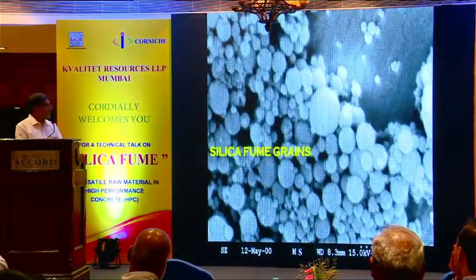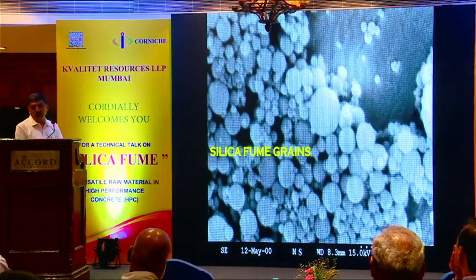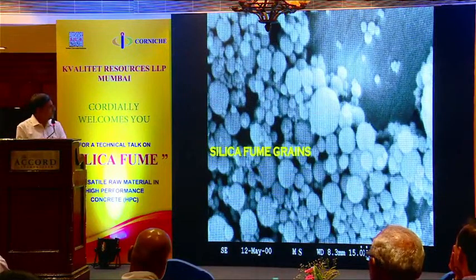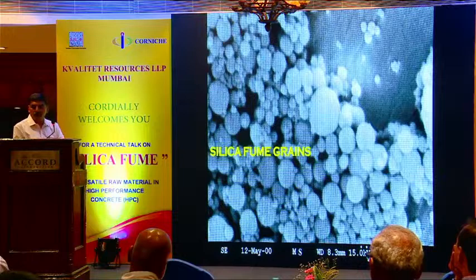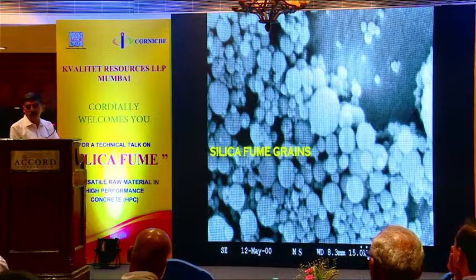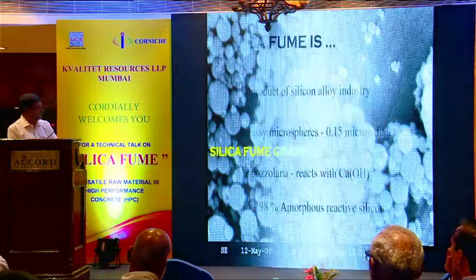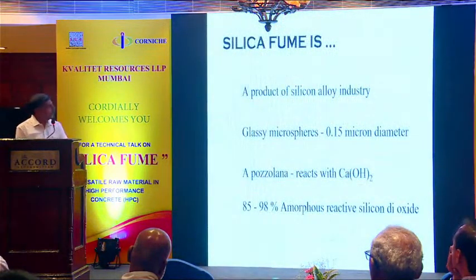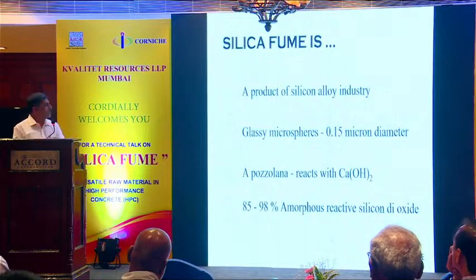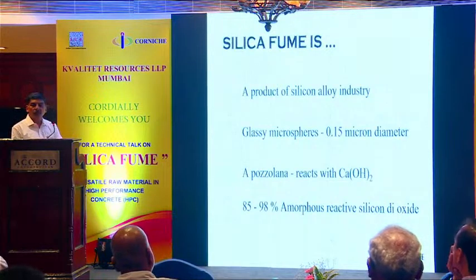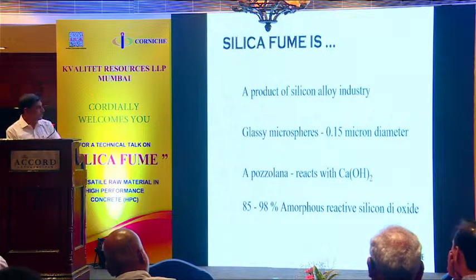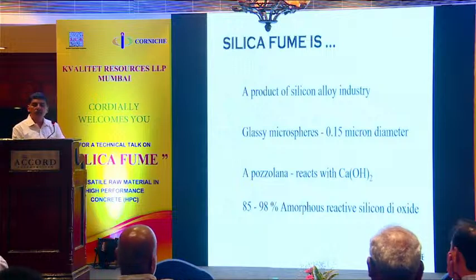How does the silica fume look under SEM? Perfect spheres, amorphous spheres, 0.15 microns in diameter. It's finer than cigarette smoke. Silica fume, a product of the silicon alloy industry, glassy microspheres, 0.15 microns in diameter, average particle size. It's a pozzolana, it reacts with calcium hydroxide. It could be anything between 85 and 98% amorphous reactive silicon dioxide.